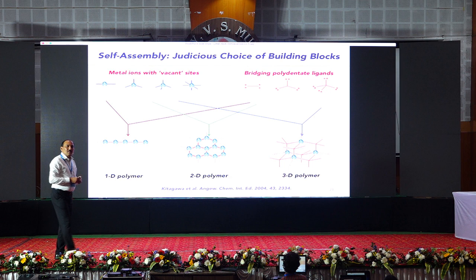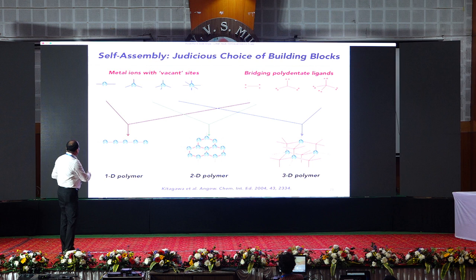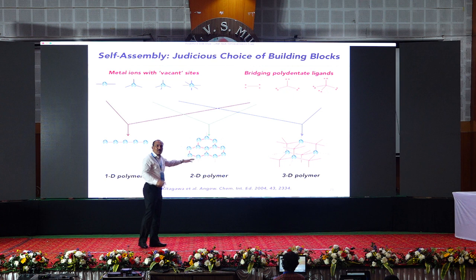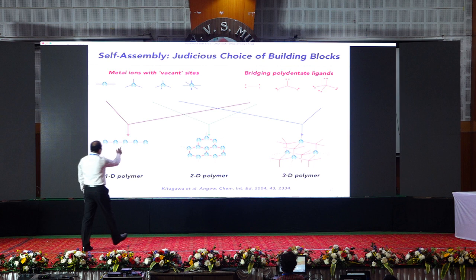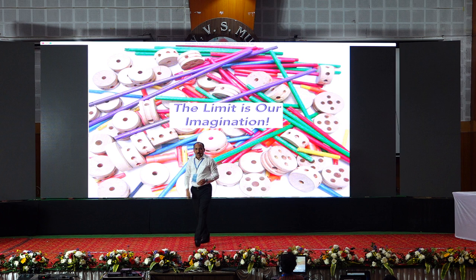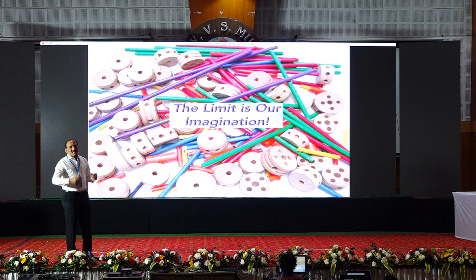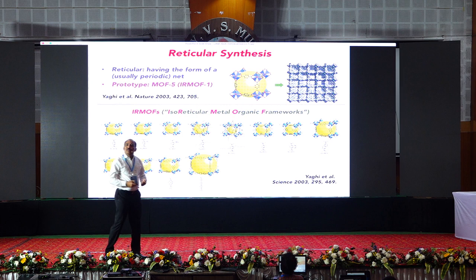If you have a metal node with, let's say, a trigonal geometry, and you take an organic linker with a trigonal geometry, you can get a two-dimensional honeycomb structure. If you have a metal node that gives you a tetrahedral connectivity, and you have an organic spacer with tetrahedral geometry, you can get a diamondoid structure. This is work that has been pioneered by Yaghi. Of course, it's like a tinker toy set. You can deal with the metals as nodes and organic structures as spacers and weave metal organic materials.